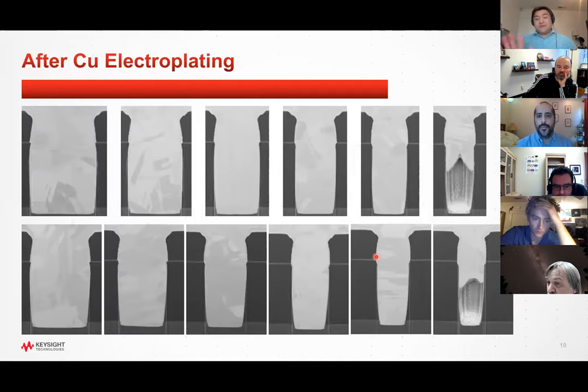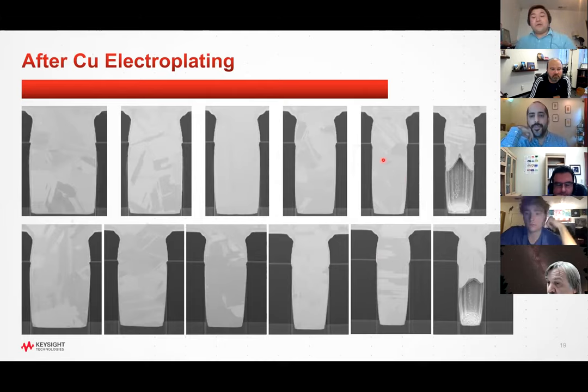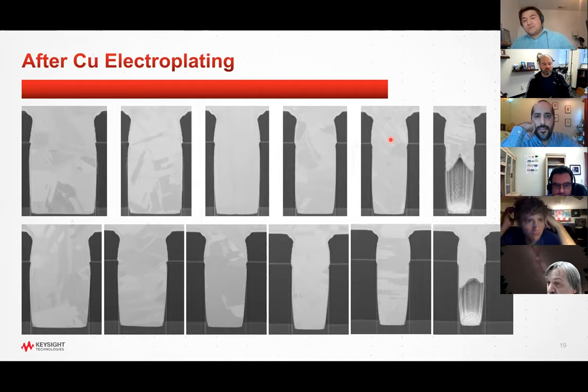And so here's some examples of what that looks like after plating. These are some test structures in decreasing size that were taken on a sample. And all of these look good, except the smallest structures that we tested tended to have voiding at the bottom because there wasn't enough there to successfully electroplate the copper. But for the most part, with the processes that we ended up with, I believe either this or this, one of these two was the actual target we were shooting for. And so we were able to successfully make these structures.